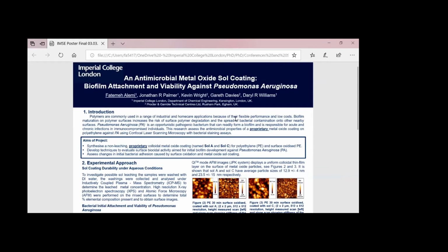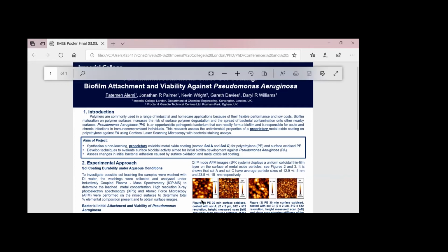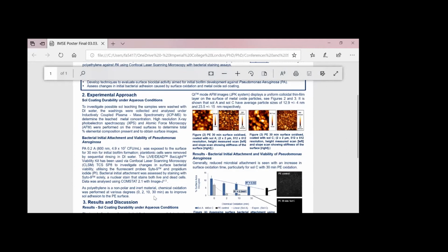We use polyethylene as a starting point because it has many uses. As polyethylene is a nonpolar and inert material, chemical oxidation was performed at various degrees to improve sol adhesion. This was done for 2, 10 and 30 minutes as a starting point.